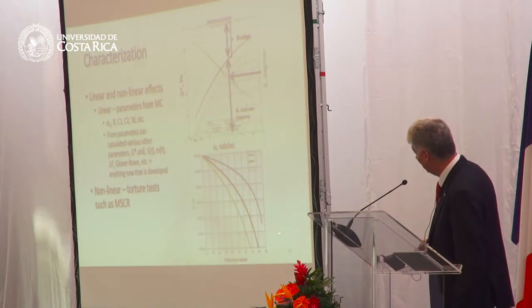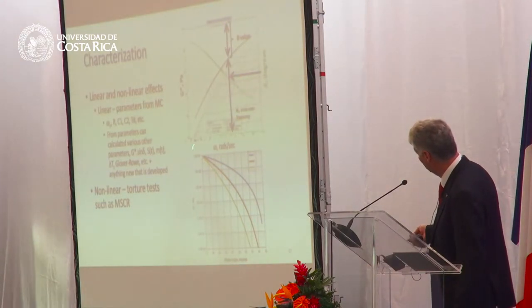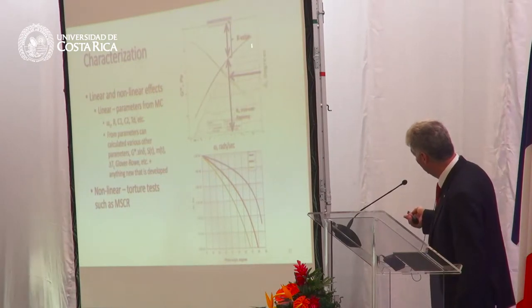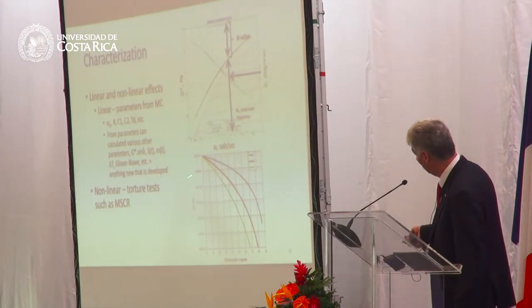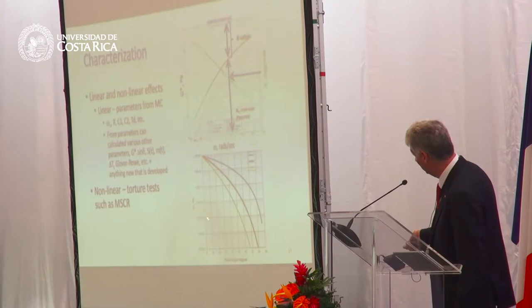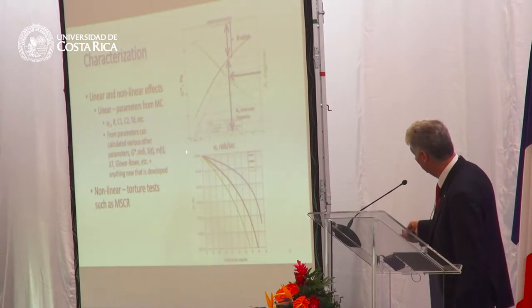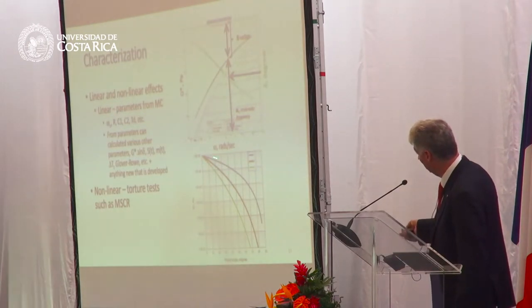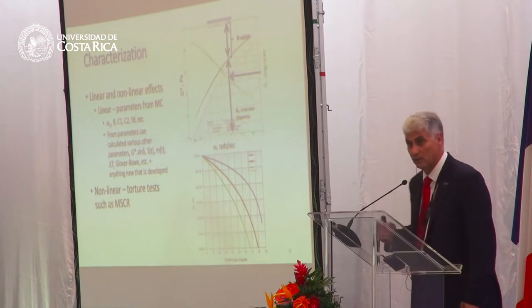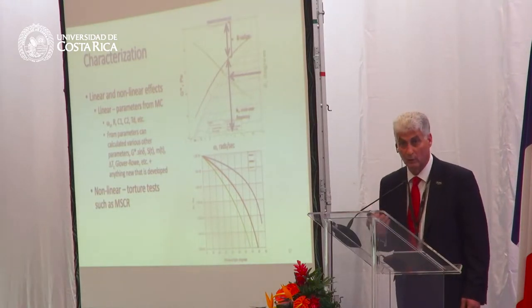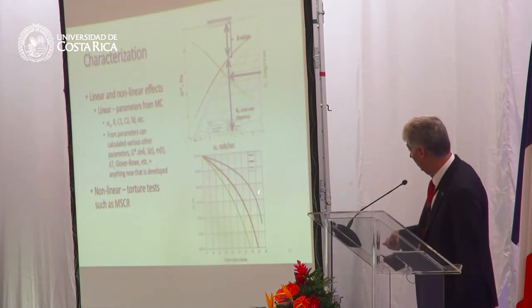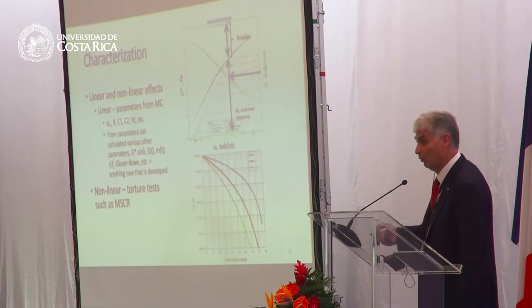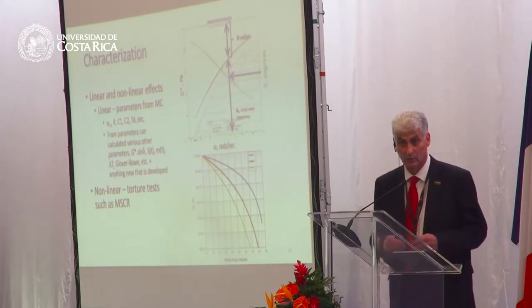If you take certain asphalt binders, I'm showing several plots like this, in this case transposed so that I'm plotting the G star against the phase angle, and each of these curves represents a binder with a different R value or rheological index. This would be more of a sol binder. This one would be more of a blown binder or a lightly oxidized binder.